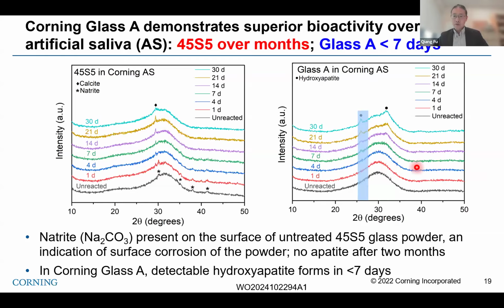For our composition, what we notice is that even around 7 days, we start to see a small peak in this XRD pattern around 26 degrees 2 theta, which shows a formation of hydroxyapatite. The peak grew higher in intensity after 1 month. So we believe our material shows a really superior performance compared with 45S5. It took months for the original bioglass to form apatite, while for our composition, it takes less than 7 days.